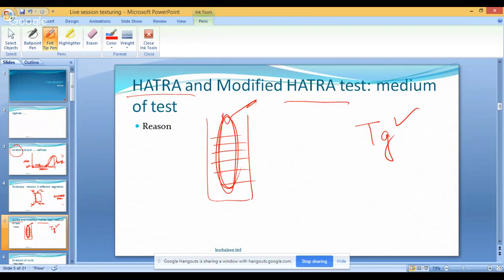Therefore, this test was modified, and you could either do a hot water relaxation where the temporary set could go before you start measuring the L1, L2, or you could put it in a hot oven. The temperature of the oven and the hot water is not very high. It is very near the glass transition temperature, so that the temporary set is removed. And this would not obviously harm or modify the final properties which you measure as crimp rigidity, because the setting was done at quite high temperatures, much higher than the glass transition temperature. So we do not expect any such changes to take place.